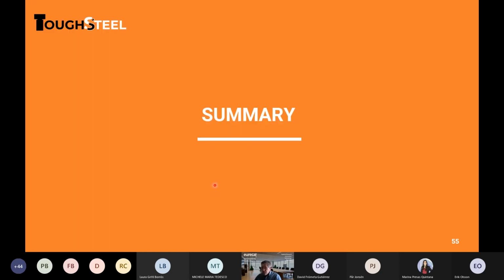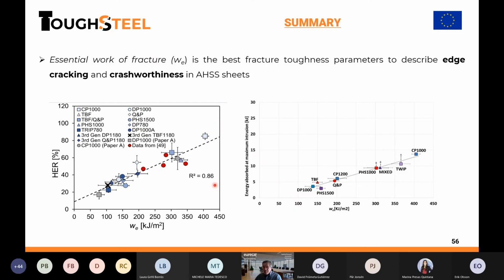Summary. The end. My summary is absolutely short because I talked a lot about properties and fracture mechanics, so I will not repeat the same. I will only say that after 10 years of working in fracture mechanics in high strength steels, after 10 years of contributing to the metal sheet industry to improve their products, we can say that the essential work of fracture is the best fracture toughness parameter to describe edge cracking and crashworthiness. Again, just the plots: many different grades, many different steels put in the same trend, also for crash.